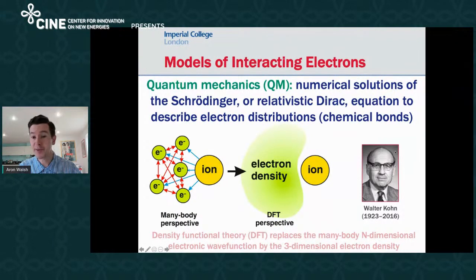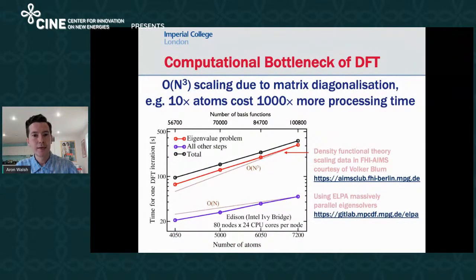And of course, Walter Kohn has to be credited with developing a number of the initial theorems that were used in DFT. So I see two big problems with DFT. One is a computational bottleneck. The underlying algorithm scales as order N cubed. That means if you want to deal with a system that has 10 times more atoms, it's going to cost you 1,000 times more computing processing time. So this introduces a bottleneck in terms of the complexity of the systems that we can model. Most DFT calculations are in relatively simple unit cells, sometimes surfaces, but we're quite far away from actually simulating realistic microstructure, even using the latest algorithms that are available.